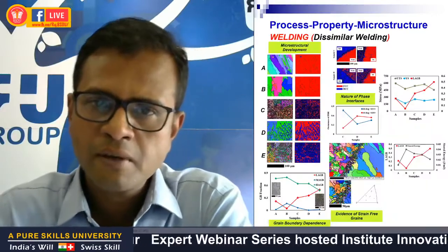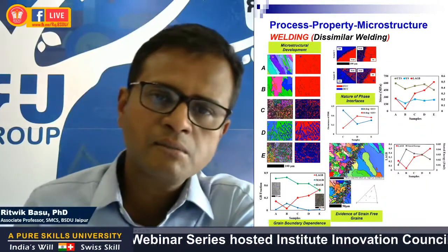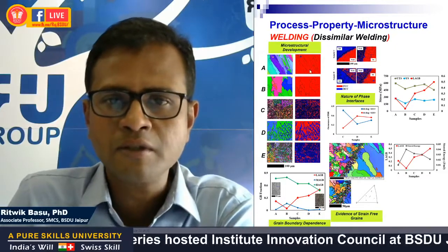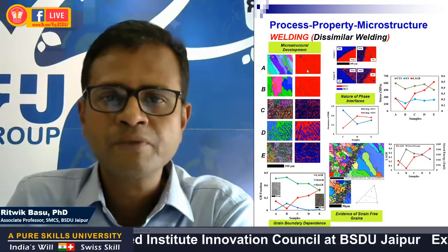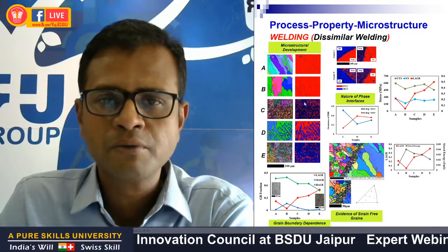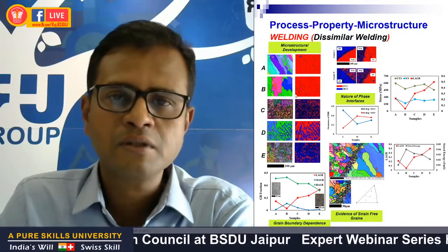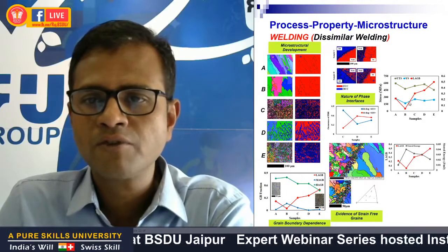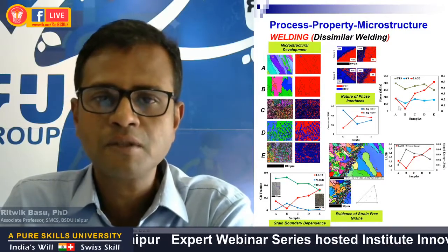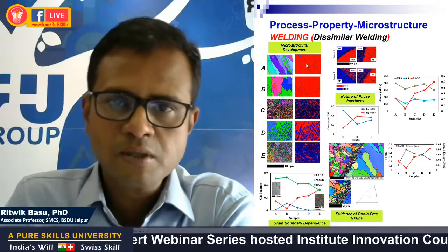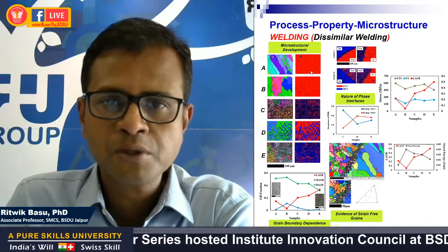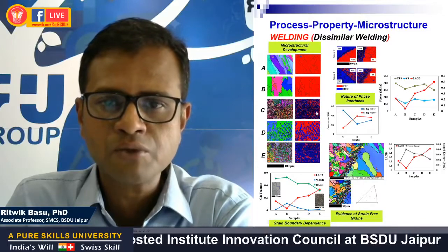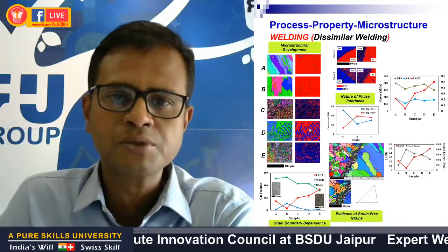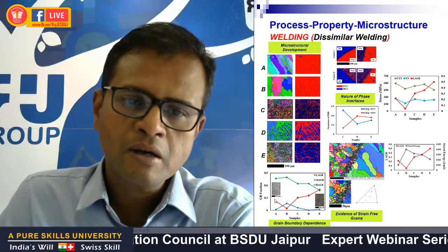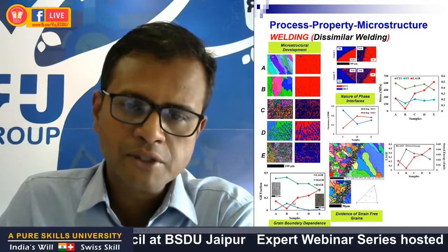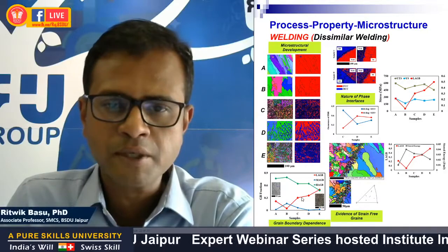So we have examined the dissimilar welded structures of steels, such as stainless steel welded to mild steel. We saw the different microstructures that were generated as a result of differences in heat input, which also led to significant differences in the strength of the material. So the microstructures were seen to vary from a large grain distribution of single phase gamma austenite to a fine grain distribution of mixed phases of gamma austenite and delta ferrite. Again, the austenite grain boundary fractions between these samples were notably different.